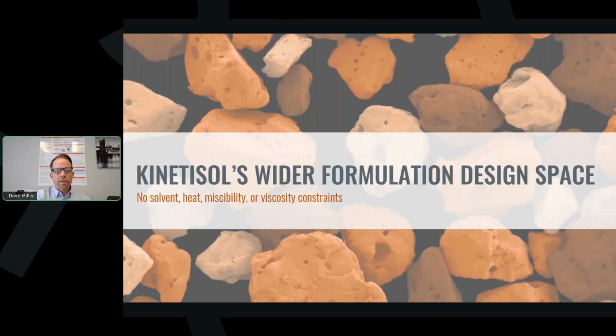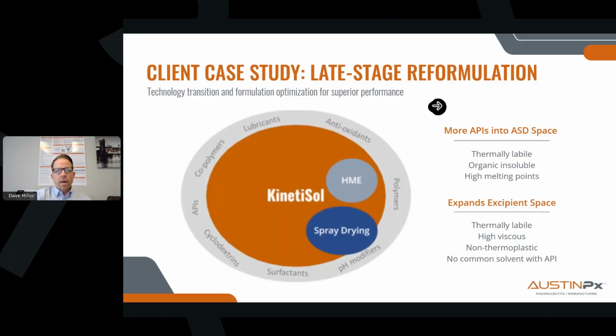Now I want to take a minute to talk about the formulation design space that's enabled by KinetiSol. It's one of the biggest advantages of the technology, and the freedom that it gives formulators to design amorphous solid dispersions specifically to the needs of their compounds. With spray drying, you're often limited by common solvent solubility, feed solution viscosity, etc. when you're trying to design a formulation. And with melt extrusion, you're limited by the thermal stability of excipients. Can they withstand the heat of the process, and also the melt rheology of the polymers? There's a certain viscosity range that's amenable to extrusion, and beyond that range, the formulations simply don't process.